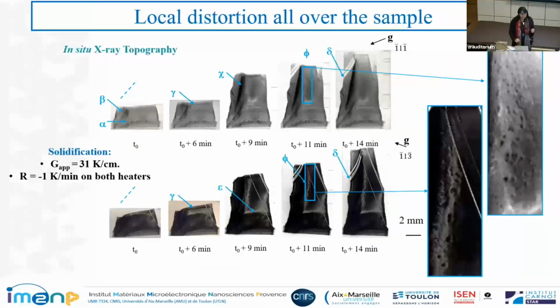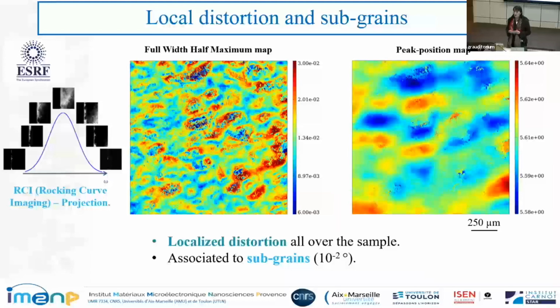I will focus on another defect. So here I just show these regions for the two spots, but in fact it's all over the sample. It's these black spots here, and we will see how we can characterize them. So they appear during solidification, but they are also observed after solidification. So they remain after solidification, and we wanted to characterize them further using the ex situ rocking curve imaging at the same place as what you've seen in situ.